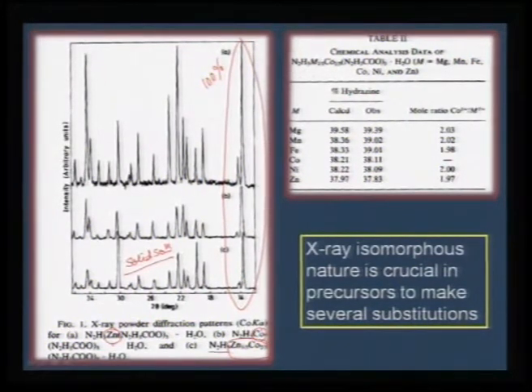So, essentially this solid solution, zinc cobalt hydrazine carboxylate, resembles both cobalt hydrazine carboxylate and zinc hydrazine carboxylate complex. As a result, we can look at the chemical analysis. Chemical analysis can give you some idea about the precursor composition. For example, I can try to calculate the hydrazine content here. As you can see, there is an excellent match between the hydrazine concentration in the complex. For example, I am talking about this N2H3. So, essentially you can make a solid solution by combining a stoichiometric amount of any metal and cobalt. So, the buzzword here is they are X-ray isomorphous. In other words, they are similar in their crystal structure. Therefore, this is crucial in precursors to make several substitutions.